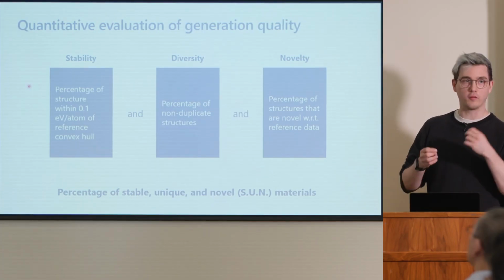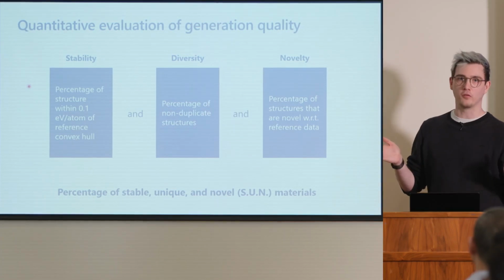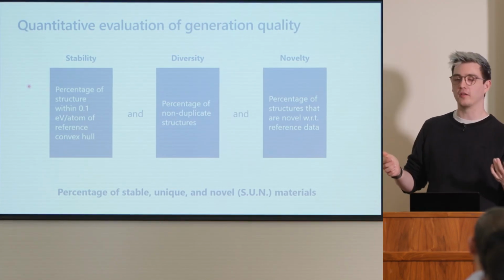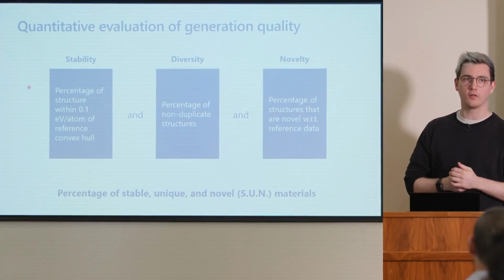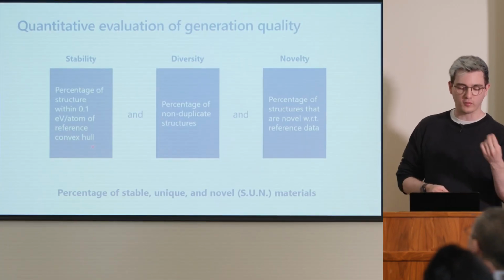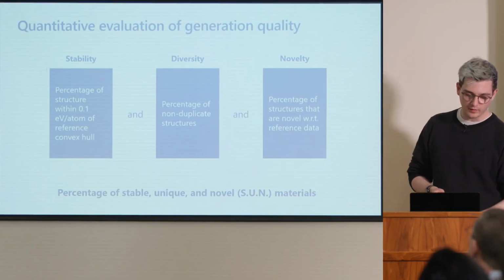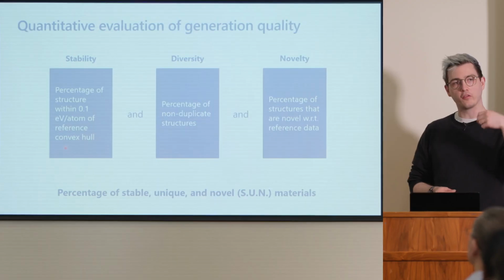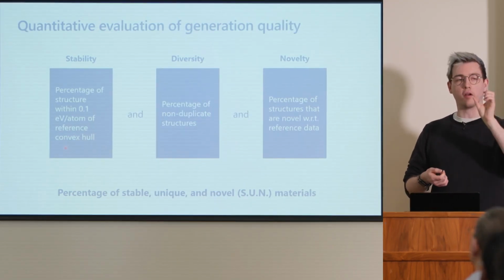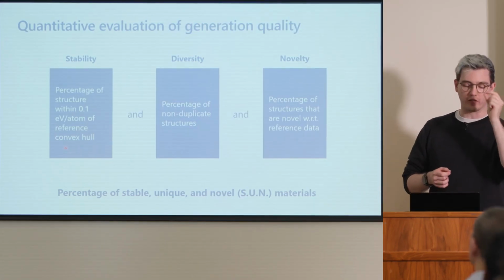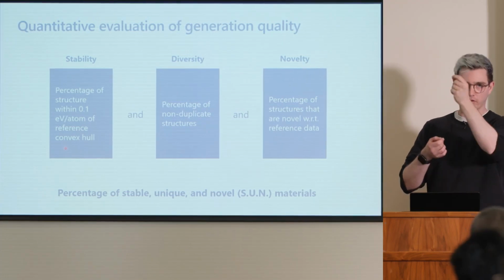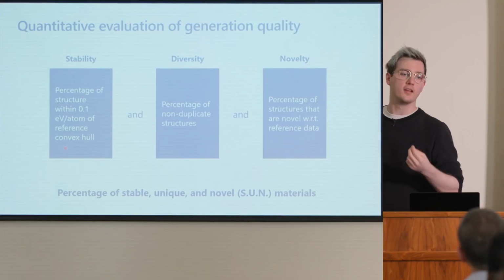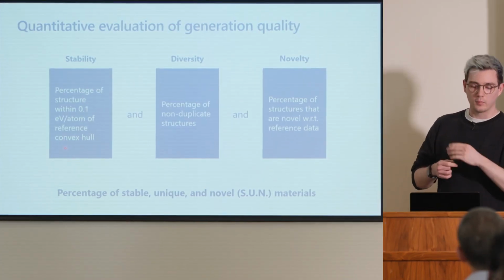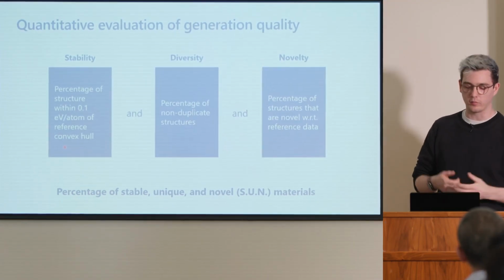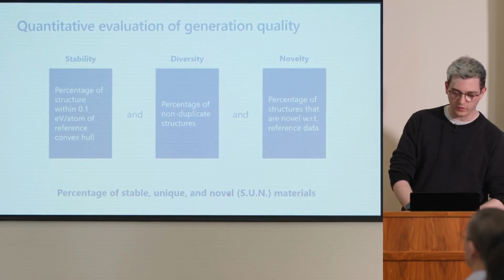So we try to approximate, and the question of whether you can make it is really impossible to answer with just computational tools. In the end, it has to be a practitioner that tries to make it, but of course we can try to use the best computational tools we have available to approximate the question of whether something is stable, can be made or not. And here this is a bit technical, but we measure how many structures that we generate are within 0.1 electron volts per atom. So this measures the energy of that structure above what we call the convex hull of the lowest energy structures. And this is, for example, like with diamond, it's not on the hull, it's not the lowest energy structure you can come up with for carbon, but still it's close enough to this hull that you can still make it under certain circumstances. So what we summarize this with is the percentage of SUN materials, which are stable, novel, and unique.